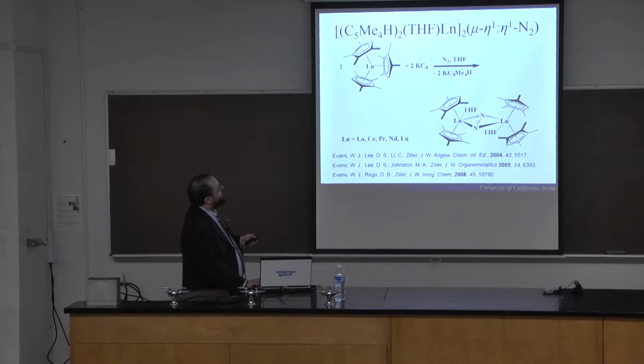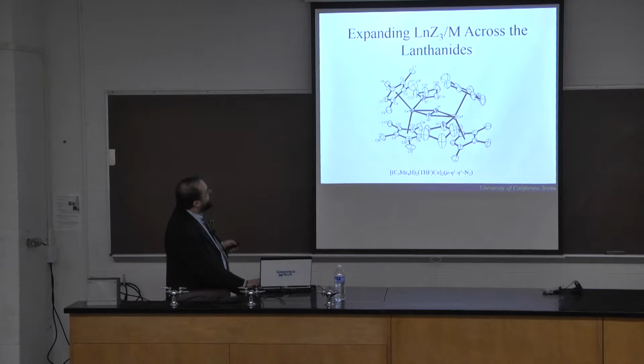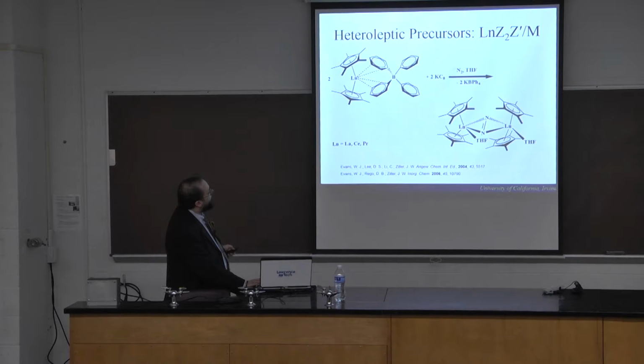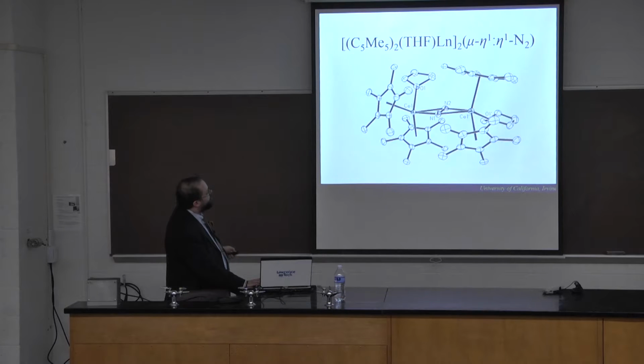Now we can get the larger ones by switching to a larger ligand. In this case, this is a tetramethylcyclopentadienyl ligand, and it will form a dinitrogen complex. Here is a cerium dinitrogen complex with the tetramethyl Cp ring. And we can also get this with the pentamethylcyclopentadienyl complex. Here is, again, the cerium example of the pentamethyl.